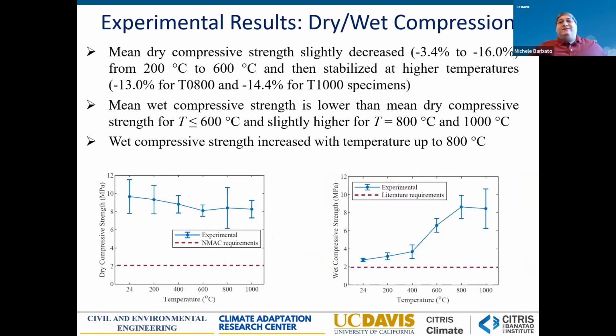However, there were other things that were also interesting. So we did these compression tests, and in the dry compression test, again, there is a slight decrease of strength from 200 to 600 degrees, and then a stabilization. But in reality, this reduction is non-statistically significant. So from a statistical point of view, there is no reduction in strength for the dry conditions.